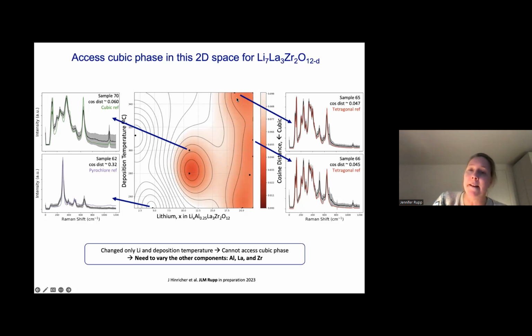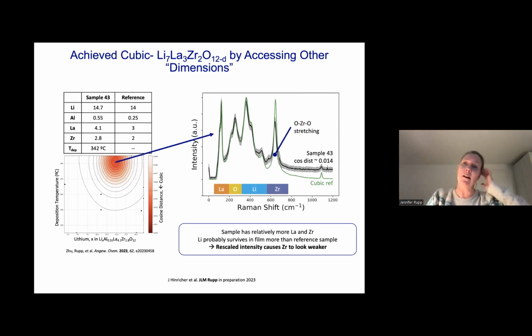And then there are some that show more tetragonal features, for instance, if you go to very extended lithiation levels, or if you stay very low. If you stay too low in lithium, and we can clearly see here where the boundaries are, then we can see that if the nominal lithium is too low, you have, which makes sense, the pyrochlore phase. And what's beautiful about it is it's now a way to have 100 samples that we can make, and we can just tailor the lithium and other cations as you want. And we can use, as we show here, the Raman spectra to show where the boundaries are. And where you have even mixed phases, you can't identify it as one or the other phase. And that is what we try currently to understand.